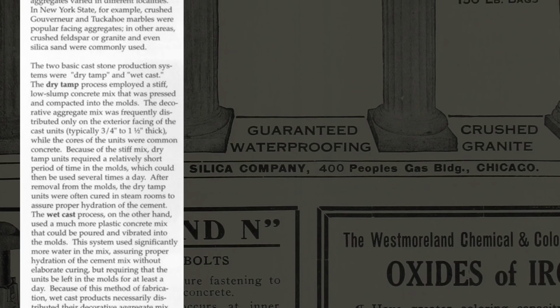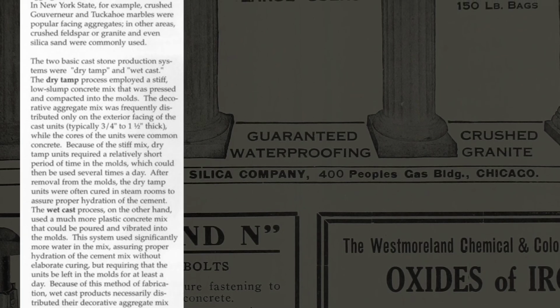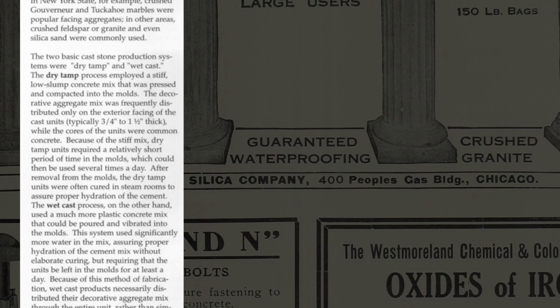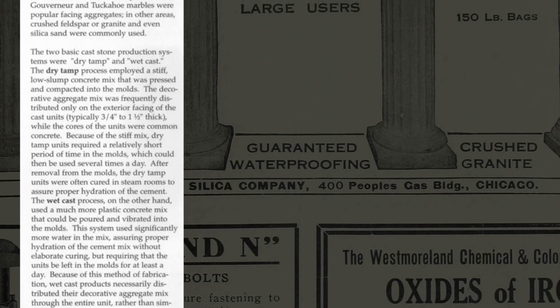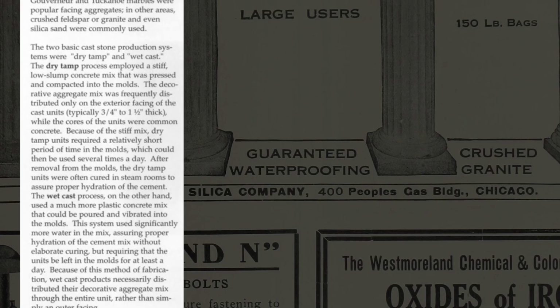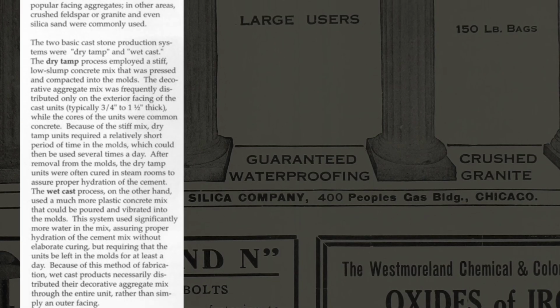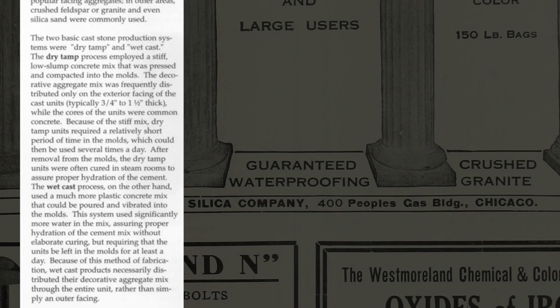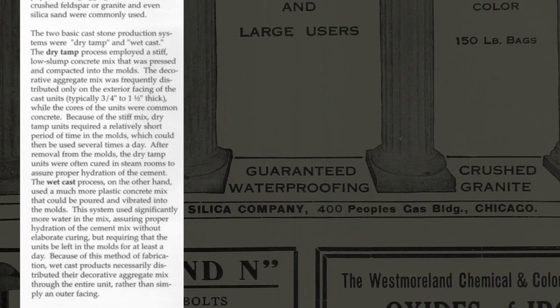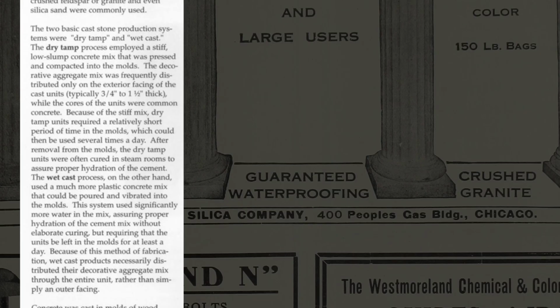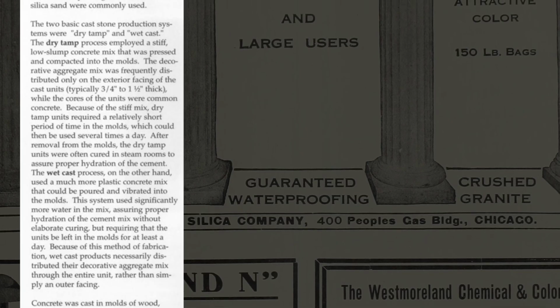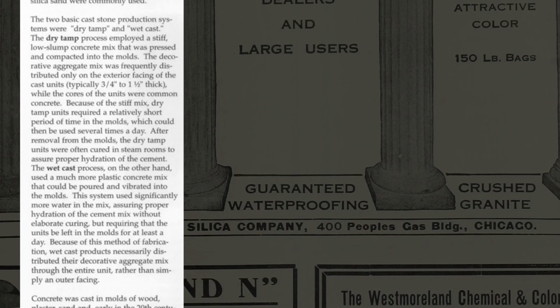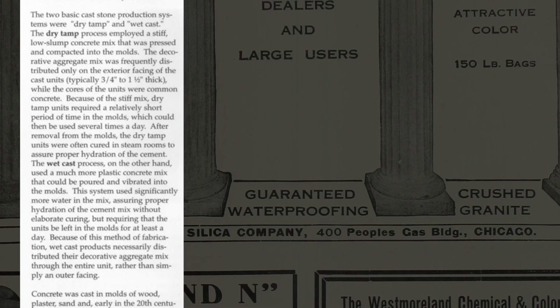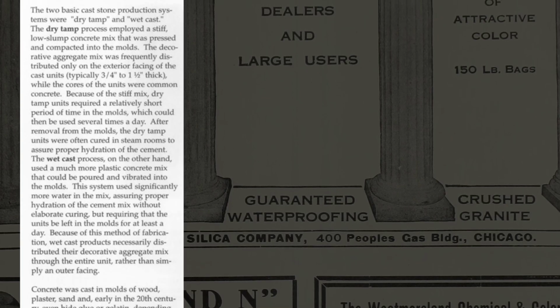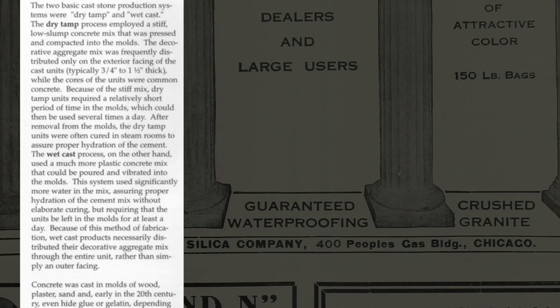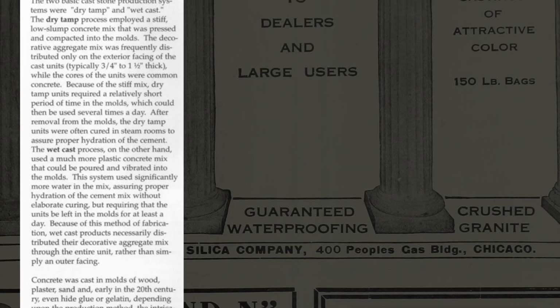The decorative aggregate mix was frequently distributed only on the exterior facing of the cast units, typically 3/4 to 1.5 inch thick, while the cores of the units were common concrete. Because of the stiff mix, dry tamp units required a relatively short period of time in the molds, which could then be used several times a day. After removal from the molds, the dry tamp units were often cured in steam rooms to assure proper hydration of the cement. The wet cast process, on the other hand, used a much more plastic concrete mix that could be poured and vibrated into the molds.